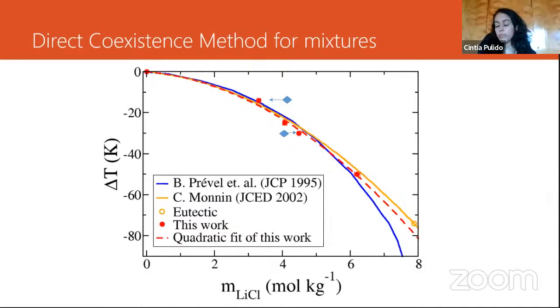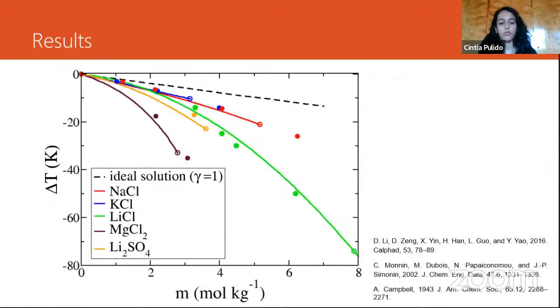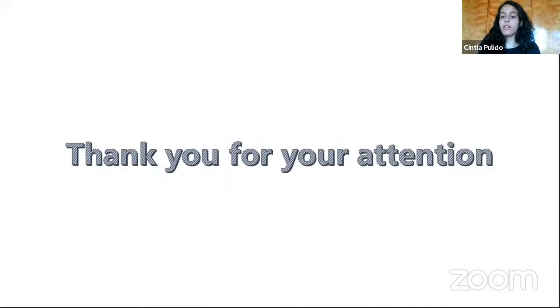Okay, in the one below, the temperature is below that of coexistence. So the concentration got raised, and now we can calculate the temperatures. We did it for different salts, and here are the results. The lines are for experiments. As we can see, the simulations predict quite well what we have seen via experiments, also taking into account that the experiments had to be fit because there was a large dispersion of the results that we do not get. And thank you for your attention.